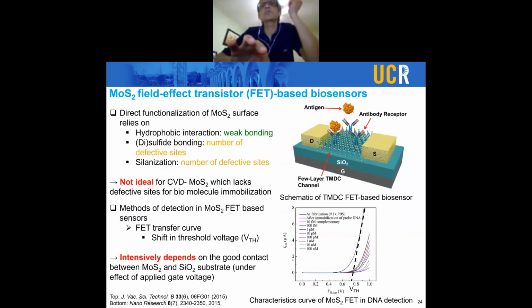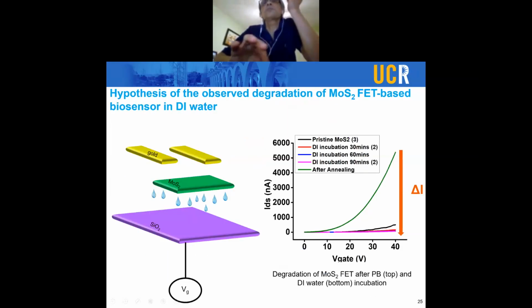These are the FET curves showing the source drain current versus the top gate potential. They claim that with increasing concentration, you can see these curves shifting. But in our experience, what we found is that by just repeating the sweeps of the gate potential with time, 30 minutes, 60 minutes, 90 minutes, without having any biological molecule there, we were still seeing a drop in the source drain current.